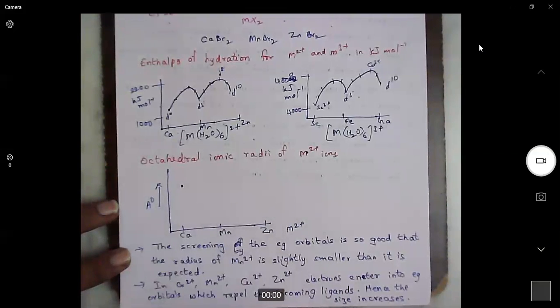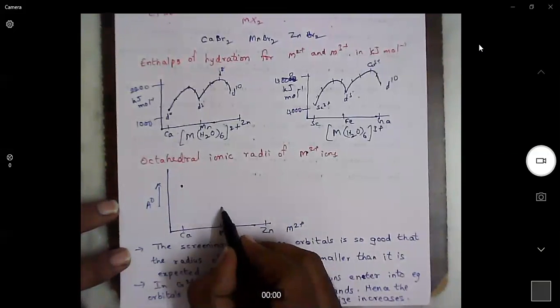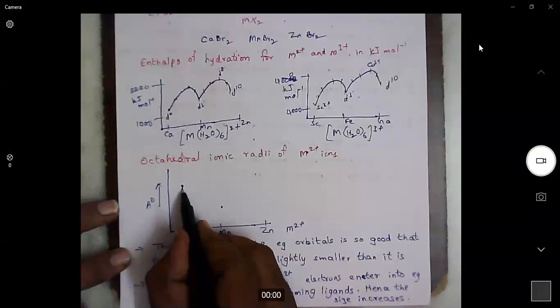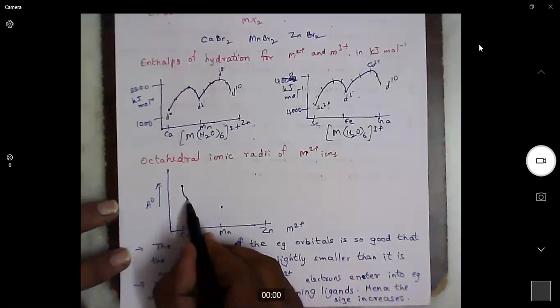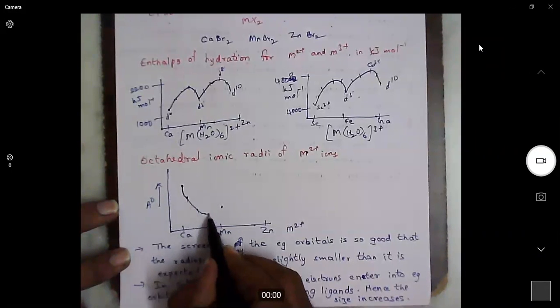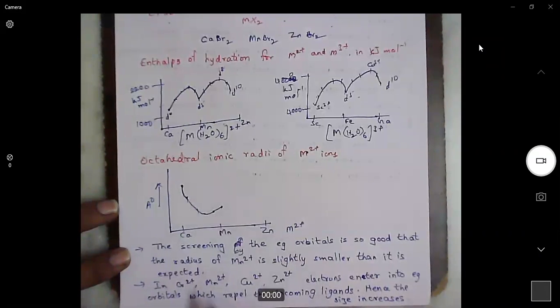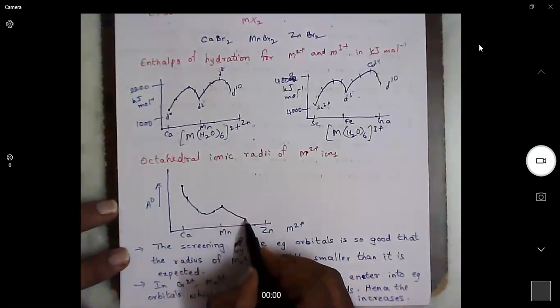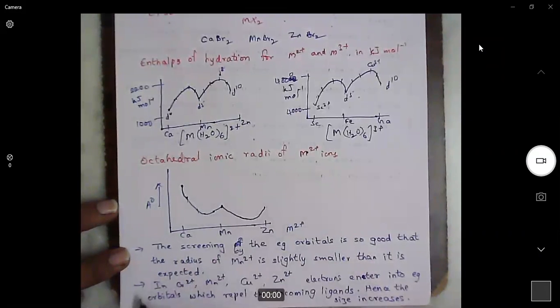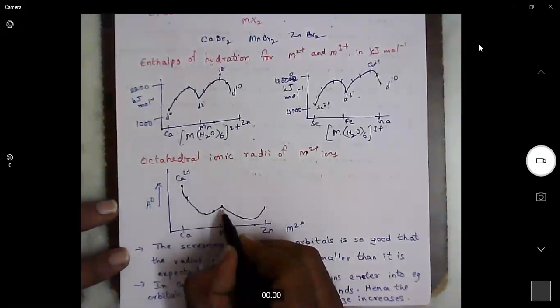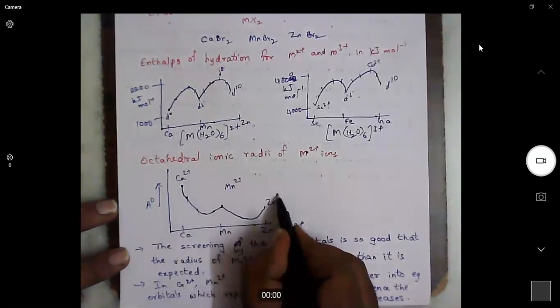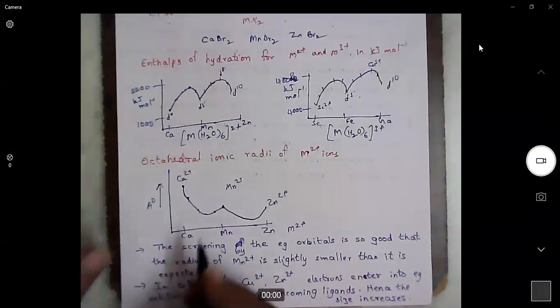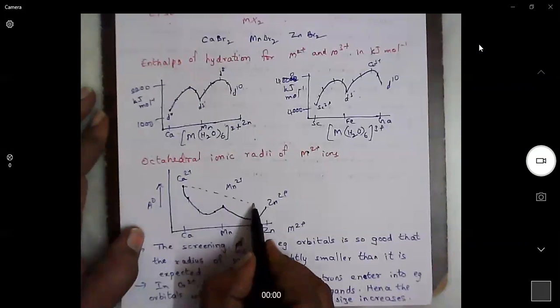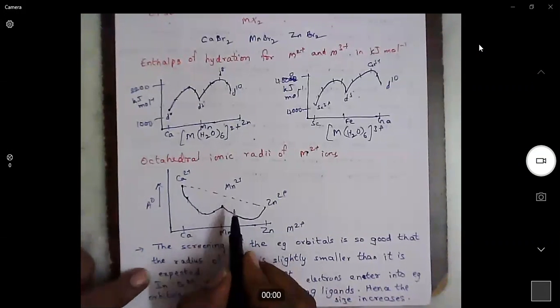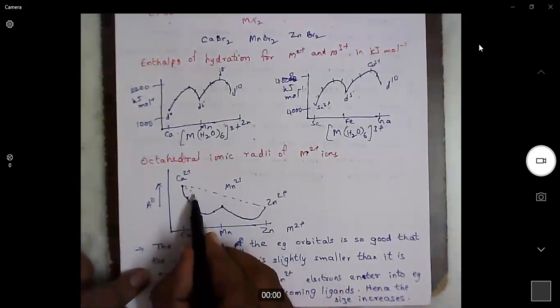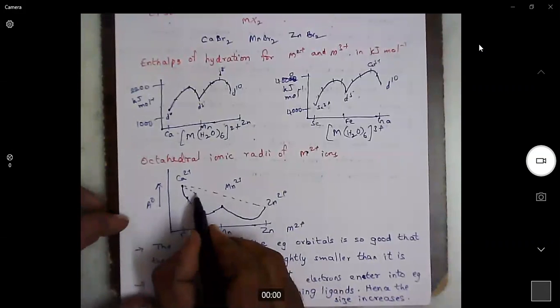For calcium, the radius is very high, then it will decrease for scandium, titanium, vanadium, then it will increase up to manganese, then again it will decrease and it will increase up to zinc. So this is calcium 2 plus, this is manganese 2 plus, and this is zinc 2 plus. Here the difference is that this is the expected trend, but this is the actual trend. The actual trend is different than expected.